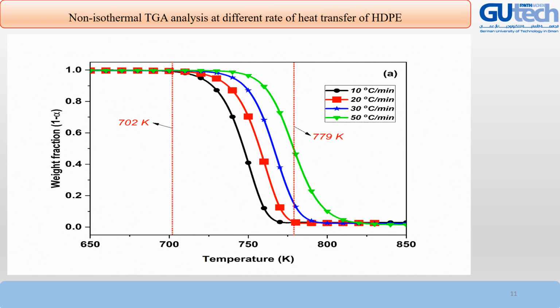To obtain the range of temperature for pyrolysis, TGA analysis has been performed for HDPE, and as you see from the graph, at different heating rates from 10 to 50 degrees Celsius per minute, the range of temperature for dissociation of the weight fraction of the feed is from 702 Kelvin to 779 Kelvin. So these are the two main temperatures for the pyrolysis. So we can find the temperature of the pyrolysis from this TGA analysis.